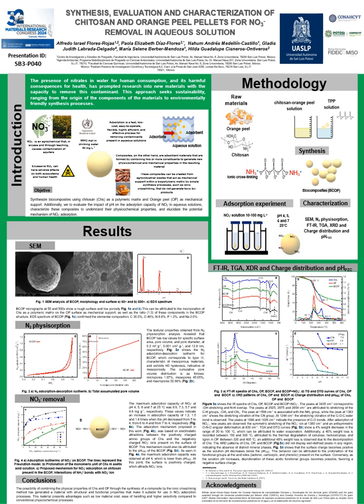Methodology. Synthesis of chitosan orange peel biocomposites. The orange pulp and seeds were manually removed, and the orange peel was washed with distilled water and a 0.01 normal hydrochloric acid solution, then dried in an oven at 70 degrees Celsius for 48 hours. The dried orange peel was then ground and sieved to obtain a particle size of 260 to 600 µm.